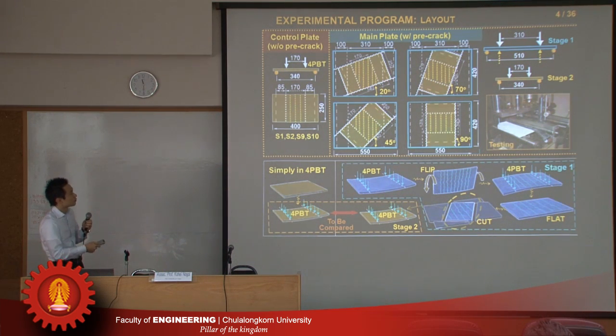So for the main plate, yes, we firstly give the bending to a certain degree of damage. Then after that, yes, we unload. Yes, we have the cracking on the bottom surface because of the bending. Then we finish once, we stop once, and flip and make it flat. And then it's a unique thing. We cut to a certain degree the specimen with some damage due to the initial loading. And then this size is the same as the control one. And yes, we do the same bending test as the control one, but with initial damage with a certain angle.